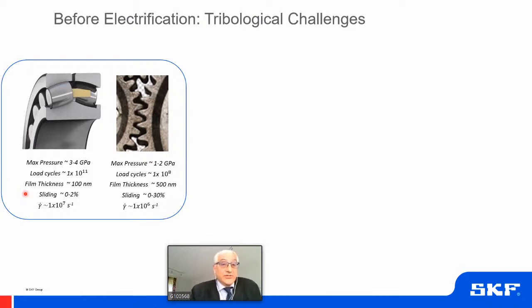Sliding conditions go from 0 to 2% in the loaded zone, and that gives us some shear rates, which are about 1 multiplied by 10 to the power 7 reciprocal seconds. This is very high shear rates. Gears work under slightly lower loads, 1 to 2 gigapascals. The number of cycles that we expect to endure is also a bit lower, 1 multiplied by 10 to the power 8. The film thickness is a bit thicker, but we need to remember that the surfaces of gears, the roughness is higher, so in reality, the lambda ratio is about the same as the bearings. The sliding conditions go from 0 to 30%, and the shear rates are a bit lower than bearings.